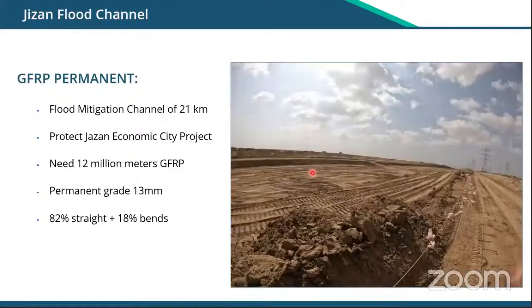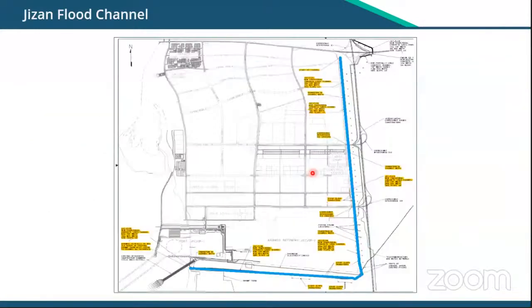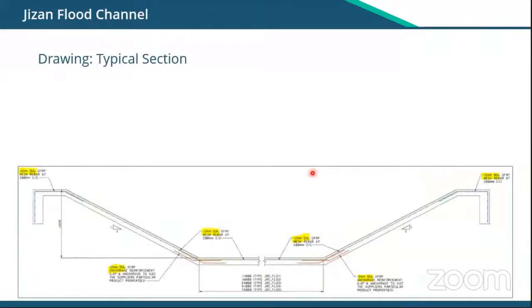This flood channel I just showed you, the blue line, is a 21-kilometer project. It required 12 million meters of GFRP bars, and you will see we used diameter 13 for the project. Most of the bars are straight bars, but you can see almost 20% of the bars were also required in bend shape.